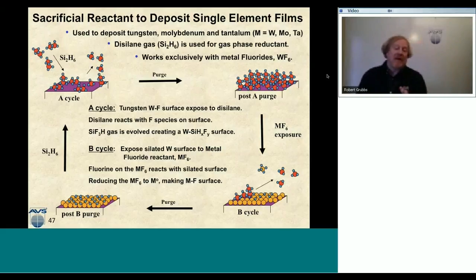But with that being said, it's pretty remarkable that you can deposit tungsten, which is a great metal to deposit, an important metal in the semiconductor industry, using ALD, and you can actually do this at a reasonably low temperature, like 125 degrees C. You can deposit tungsten metal. So that's very exciting. So this is one method on how to deposit a single element, and that's using disilane as a reducing gas, making a multi-fluorosilated species. But mind you that it only works for 3 metals on the periodic table.